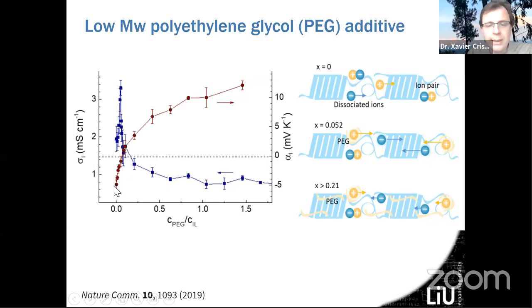But when you add this polyethylene glycol, you see that the Seebeck coefficient goes towards zero and crosses to the other side, up to +10 millivolt per Kelvin. So basically, by adding this polyethylene glycol, you promote the transport of the cations, which become very well transported. So by controlling the composition of these gels, you can change the Seebeck coefficient from minus to plus, which is quite interesting, because that's what you need to build thermoelectric modules.